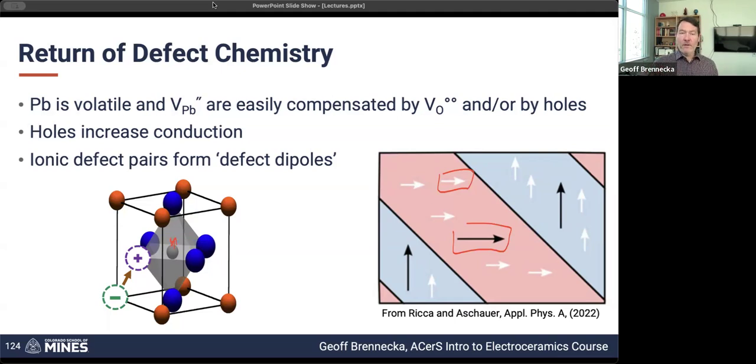You're getting a slightly off-center shift of the ions. They're not actually having to hop full lattice spaces. Because these built-in defect dipoles are based around the ionic vacancies, or in another case an actual 3+ ion on a 4+ site, they're going to be much, much harder to move around, because it requires things actually hopping a full lattice position.